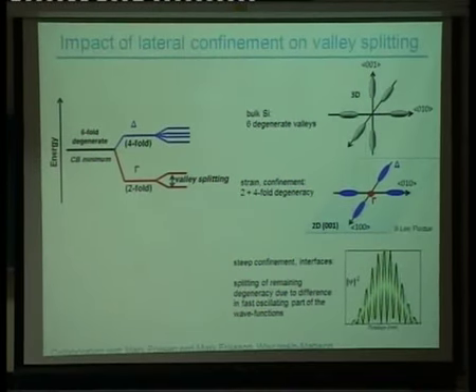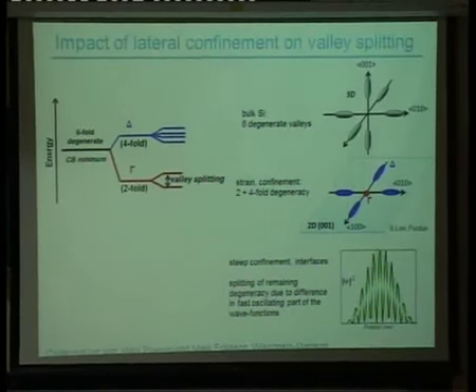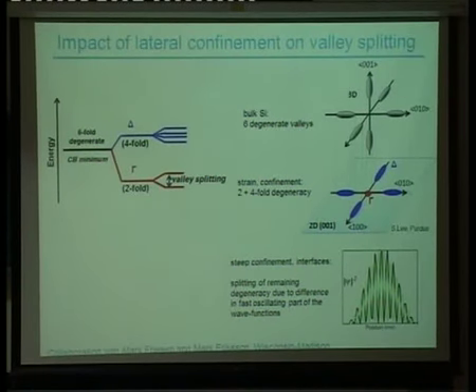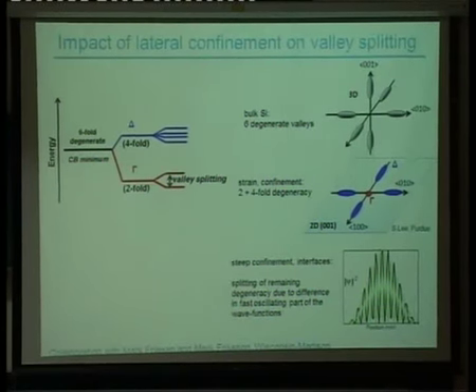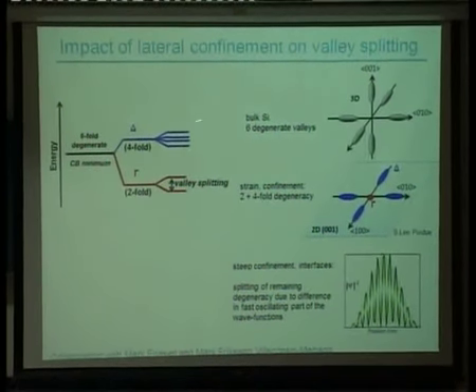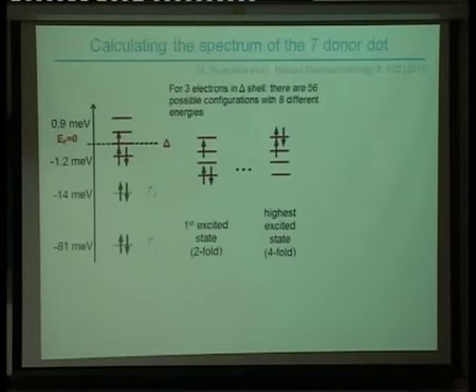So the key thing is we've got these very highly doped structures. In this dot, where we know that we've got 6 plus or minus 3 phosphorus atoms, you can start to populate these valley states with the electrons. You can put 4 in here, and the remainder would go in these delta bands at the top. There are actually 56 different possible ways you can put these 3 electrons into these delta band states. And if you work out, as we did with Mark Erickson and Mark Friesen from the University of Wisconsin-Madison,